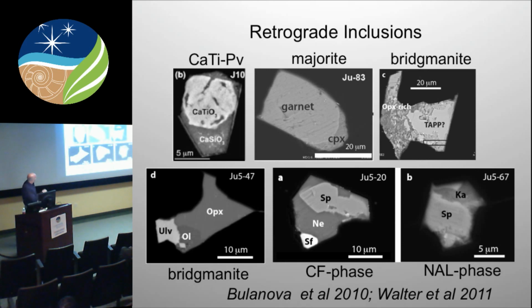Anyway, so we find this wide range of compositions. When you put them back together, the two most common ones that we find are majoritic garnet. So here's a garnet and a clinopyroxene that's unmixed from that. You put that together and you get a majorite. And calcium perovskites of various flavors. And they tend to be titanium-rich calcium perovskites. I'm going to concentrate on these two today.